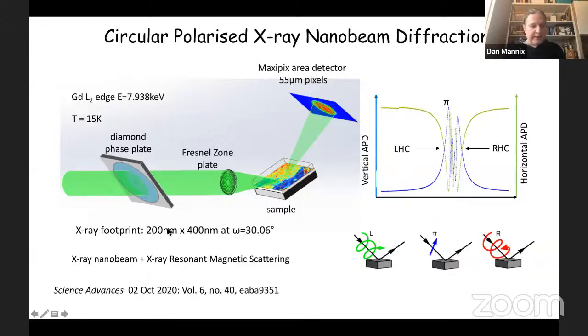It's interesting to note in passing that these experiments were taken at the old ESRF, before the upgrade. So now if we go back to ID1, using similar optics, what they can achieve with this very high emittance source is something like a 30 nanometer beam spot. So you gain an order of magnitude in the beam size just from this new source, before even talking about the increase in coherent flux. That is also a very great parameter, because our resolution in the scanning diffraction is related to the beam size. So if we go back to ID1, and we do have experiments to go back on ID1, just by using this smaller beam size, we should already increase our resolution.